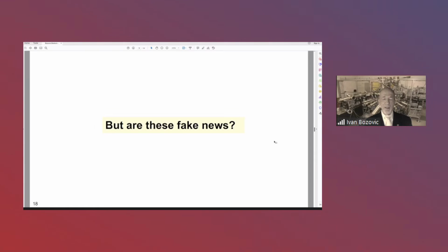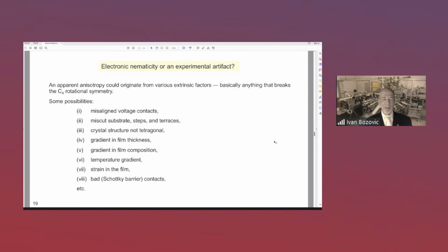Precisely because angle-resolved transverse resistivity measurements are so sensitive, they will also pick up any anisotropy that is caused by some extrinsic factors. For this reason, we assembled a list of all possible artifacts. Some of these are listed here. And then we check them and rule them out one by one through extensive and dedicated experimentation.